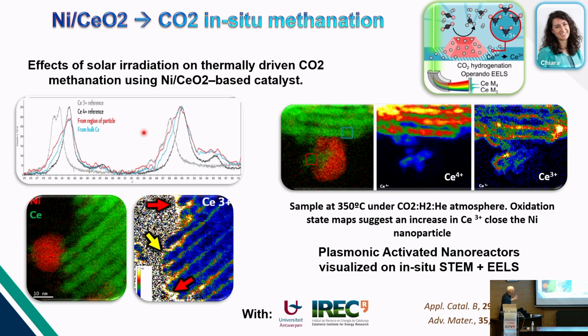But you can also move and do it in situ. In this case, what we did is applying a gas inside the microscope. So we wanted to do methanation inside this microscope. And the idea was, in 2021, we could publish this paper in which we were theorizing the mechanism. In fact, we were applying ceria, which is the base substrate, and then nickel nanoparticles, which have nice plasmonic properties. And under illumination, what we were looking at is that when you were applying hydrogen together with CO2, you were getting methane at the end of the reaction.